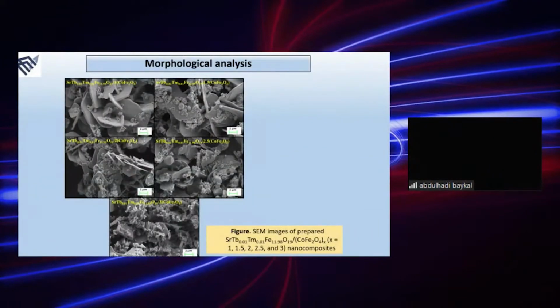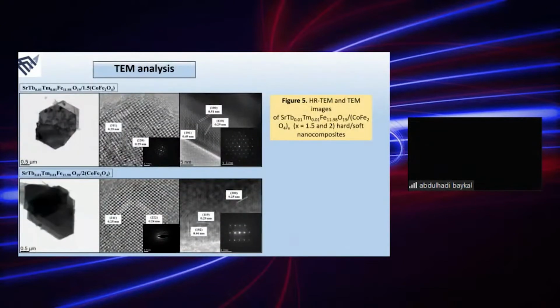These are the SEM images, scanning electron microscopy, of our 5 products. Now, with the help of the high resolution TEM that we have here, it is possible for us to look at the deep morphology. We can get deep morphological information, and also we can look at the lattice spacing as given here. You see this calculation, and this is the selected area electron diffraction pattern for x is equal to 1.5.